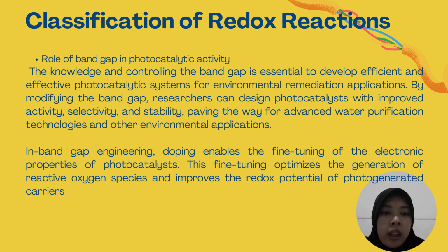For instance, narrowing the band gap of metal oxides such as titanium oxide or zinc oxide can significantly improve their photocatalytic performance by enabling enhanced solar spectrum utilization. A smaller band gap allows the material to absorb a broader range of visible light, thereby generating more electron-hole pairs that participate in redox reactions.